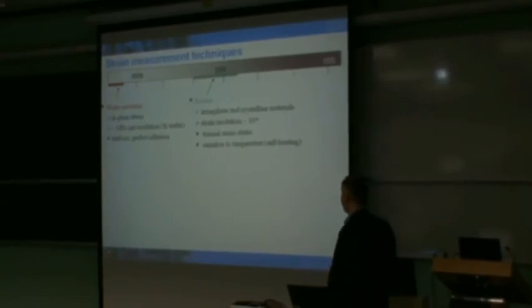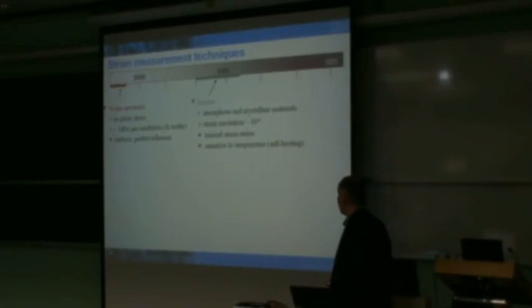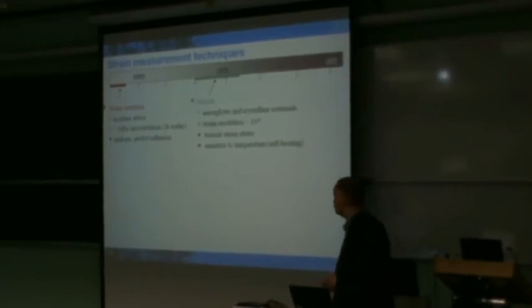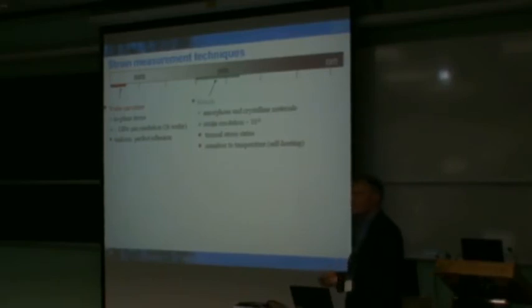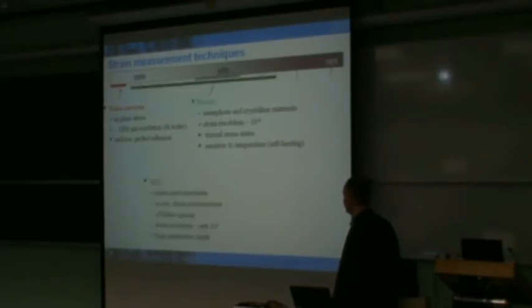When we look at other techniques that are indirect in terms of the analysis of the strain, one that has seen a lot of work in the past 20 years is based on Raman microscopy. One of the benefits is that you can interrogate amorphous and crystalline materials. The strain resolution is reasonable, 10 to the minus 4. But accessing systems that are much more complicated than uniaxial or biaxial becomes a bit tricky. Because this is a laser-based technique, you can also heat your sample and induce a change in the peak you are interested in, so there are certain artifacts that have to be considered.